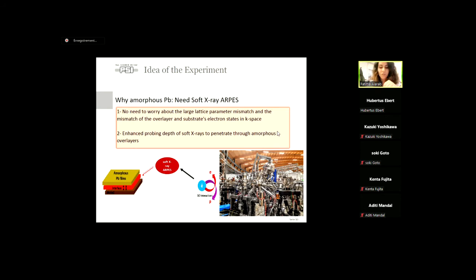And the second thing, it's very important that we use the amorphous lead. So then we don't have a momentum dependency related to lead overlayers, because if it's the case, then when we do the measurements, we're gonna get an overlap of the dispersion from the substrate, but also from lead overlayers, and then both wave functions and dispersions will be overlapped, and then we cannot really recognize one from the other. This is not good. That's why we prefer to use amorphous overlayers, where there's no k dependency, and we're gonna get some background that you're gonna see later in the measurements, and it doesn't bother us to only see the dispersion in the substrate.